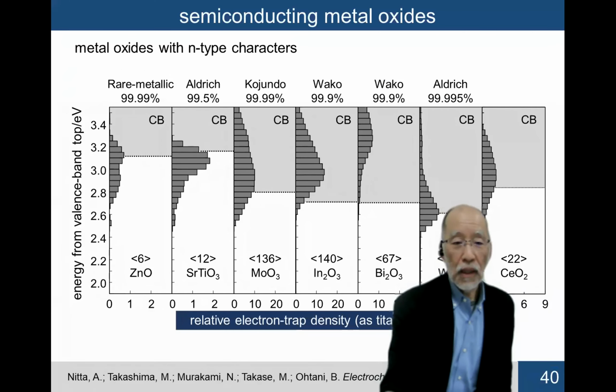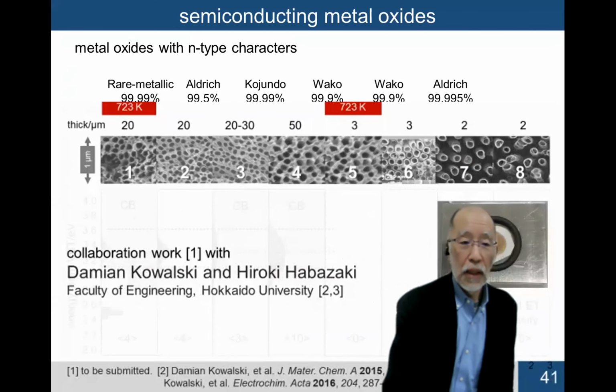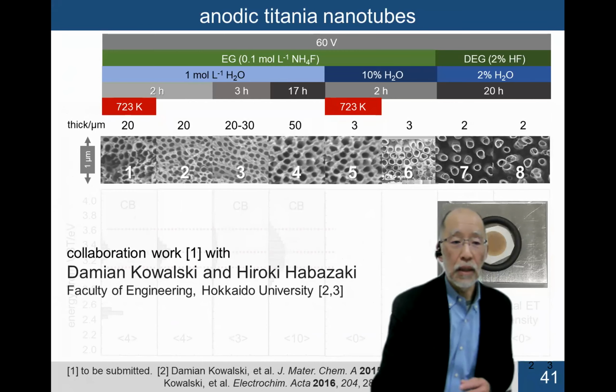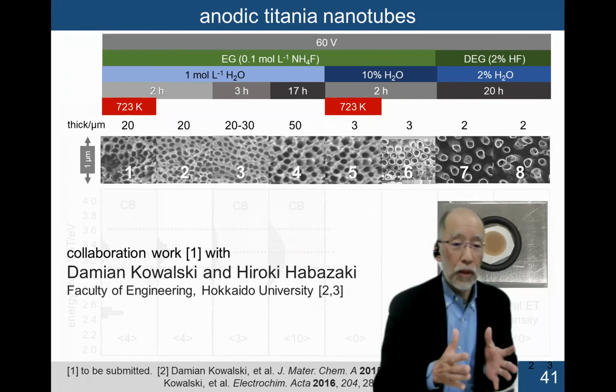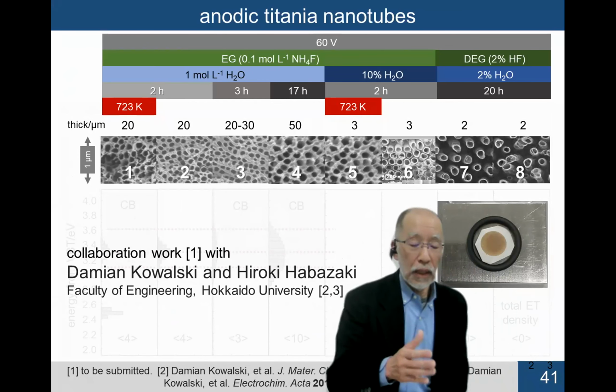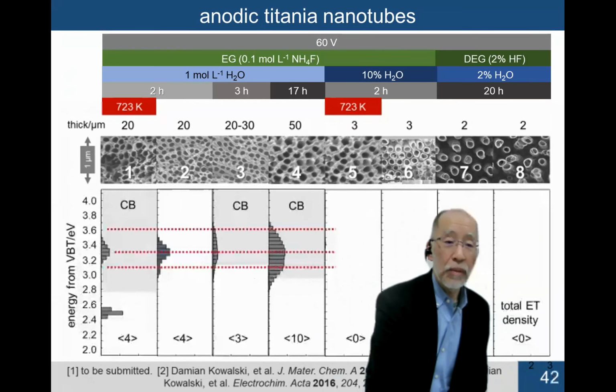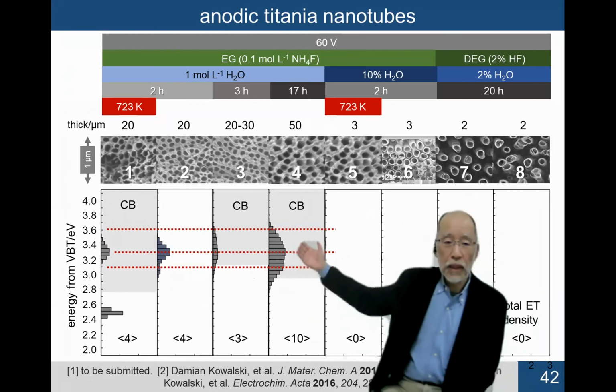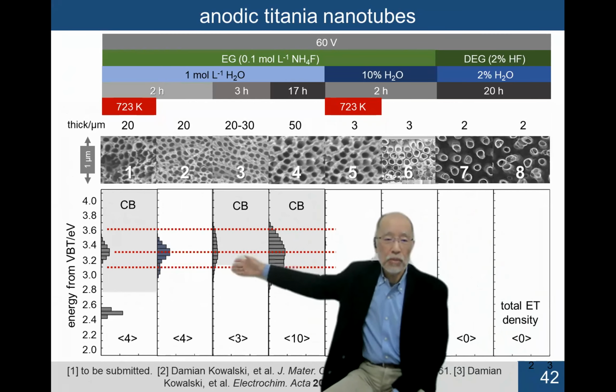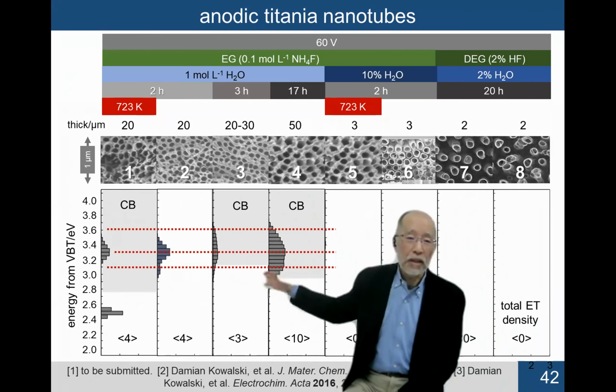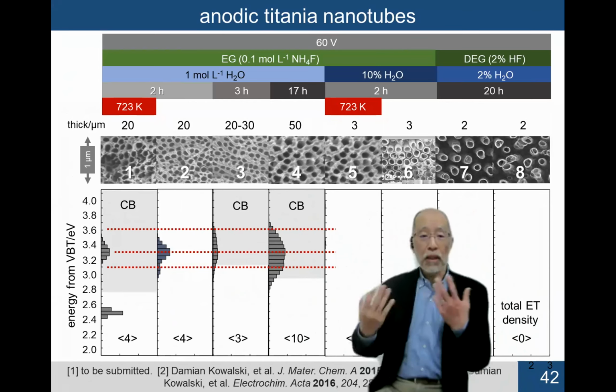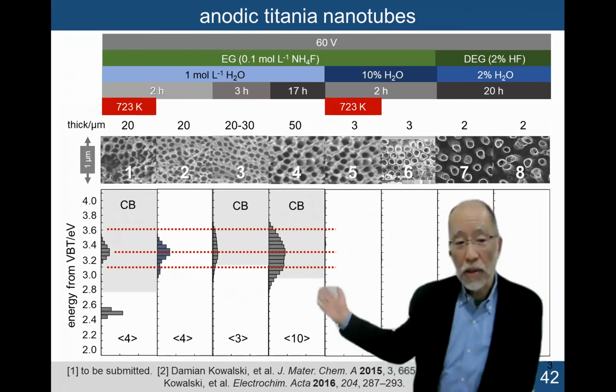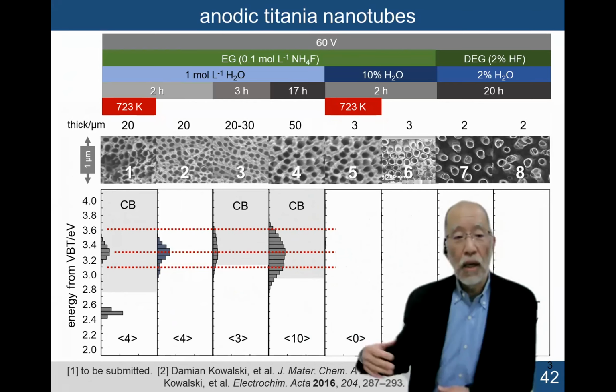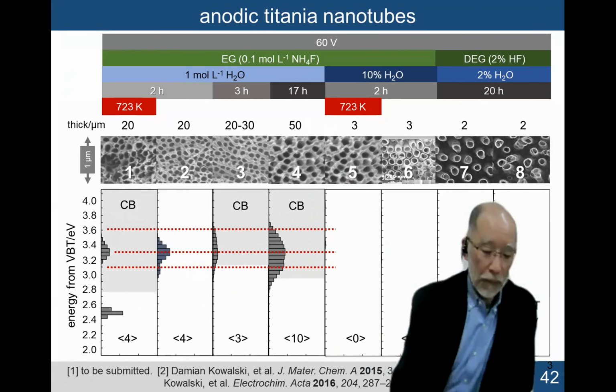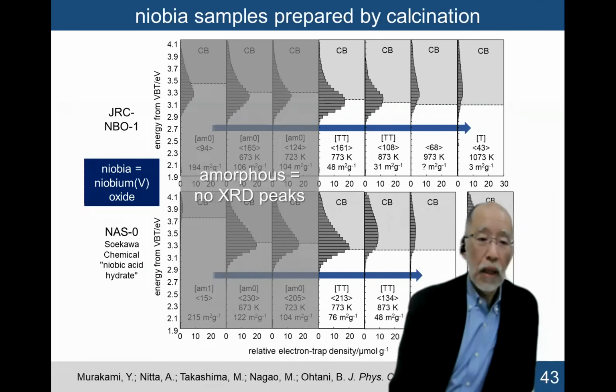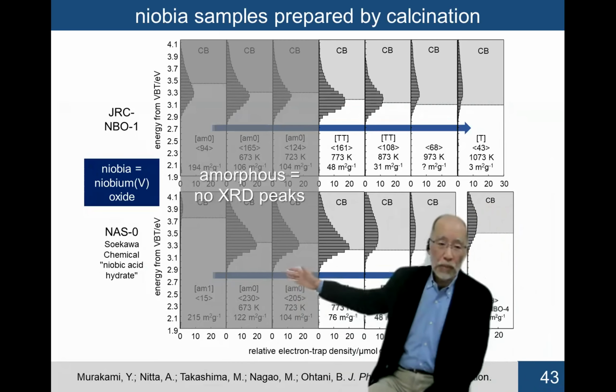So then another kind of metal oxide is the titania nanotube, prepared by anodization of a metallic titanium plate. For thicker samples, it is possible to obtain such a pattern, and they are different from each other depending on the preparation conditions. This is the first example showing such a difference depending on the preparation conditions. And even an amorphous sample can be measured.